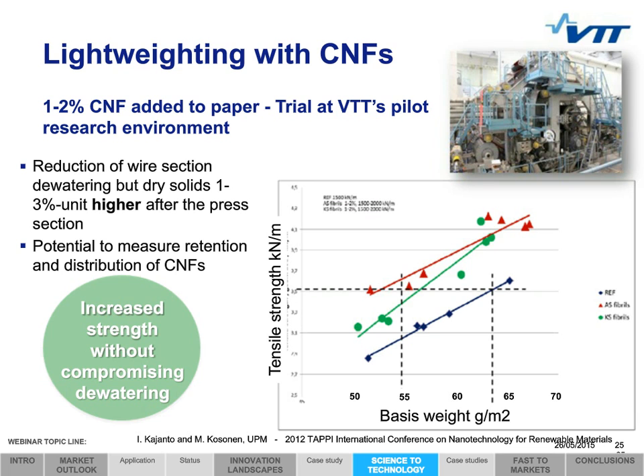The common fear in using cellulose nanofibrils in paper and board making is the problems in dewatering. However, our pilot-scale trials, together with the customer, have shown that although the dewatering can be reduced in the wire section, after the press section, the solid content can actually be higher when cellulose nanofibrils are applied. Both tensile strength and the elastic modulus have increased with CNF addition, thus enabling reduction in the basis weight.